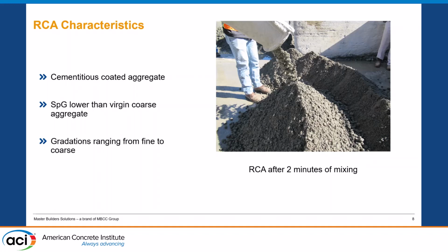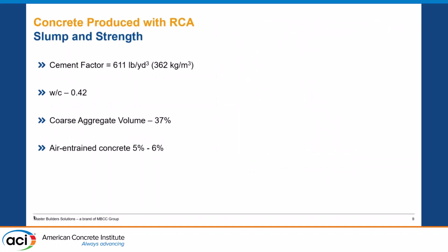So having those aggregates in hand, we ran several concrete trials in our laboratories back in Beechwood, and I will show compilation of data of some of those, or at least in one of those cases. Here the virgin, or the reference mix, had a cement factor of 611 pounds per yard. The water cement ratio was set at 0.42. The mix had a coarse aggregate volume of 37%, and we did air entrain the mix. So we were shooting for about 5.5% air, so we got somewhere in there. This concrete mix was then treated with the admixture and the aggregates generated. And through the following days, we did several new concrete mixes by replacing the coarse aggregate volume of that reference mix with anywhere between 10, 20, 30% of the recycled aggregate.